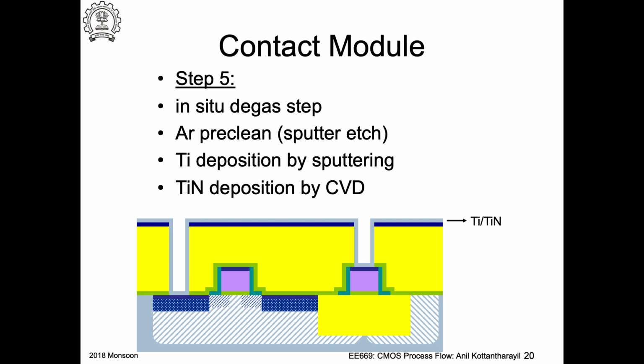So you may ask, what is the role of this titanium nitride? Why don't I just continue with titanium? The good thing about titanium nitride is actually thermally very stable, okay, can stand very high temperatures, and then it's a very good diffusion barrier. So that is a very important thing. Many of these, titanium nitride, tantalum nitride, tungsten nitride, are actually very good diffusion barriers. At the same time, they are actually quite good conductors. Yeah. So that is a very important consideration.